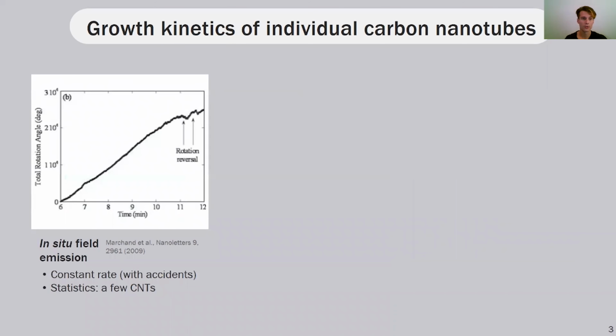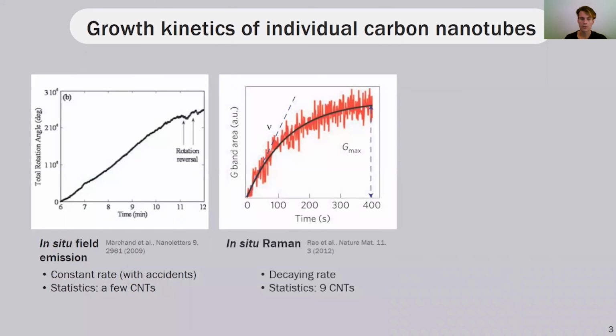Till now, several approaches were proposed to answer these questions. The first was proposed by Marchand and his colleagues, who used in-situ field emission microscopy and evidenced constant growth rates with several accidents. Another approach based on in-situ Raman was developed by a group of Benjamin Riemer in the United States and Vincent Jourdain in France, and they measured growth kinetics as the derivative of the nanotube G-band area.